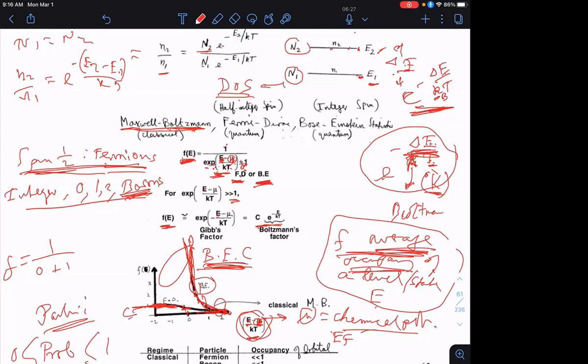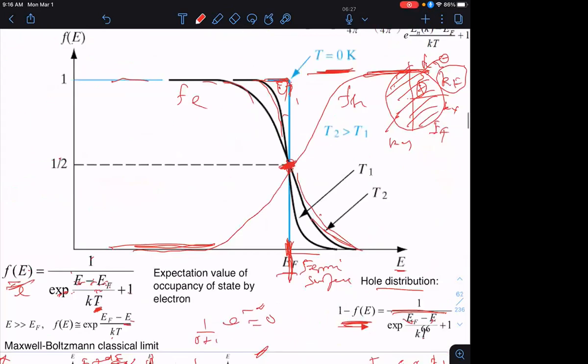Okay. This Fermi-Dirac distribution function we then plotted in a magnified version over here. Now I'm showing it not as a function of E minus mu over kT, which is a normalized way of showing the energy, but as a function of energy itself. The mu in the case of fermions is also known as the Fermi level. So that's the distribution function: e to the power E minus mu over kT is now written as e to the power E minus Fermi level over kT, plus 1.